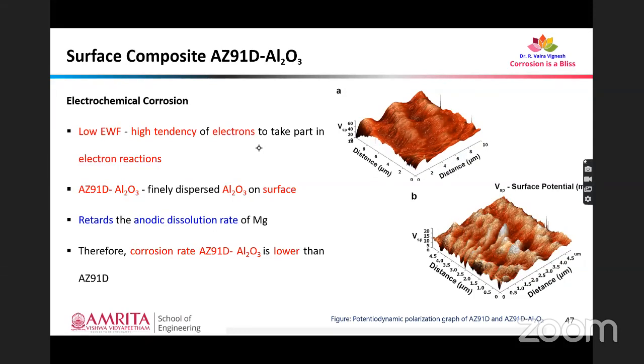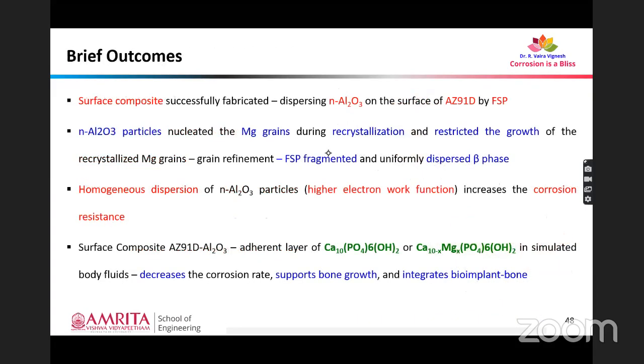So here is the surface potential map that is obtained from AFM, atomic force microscopy technique. Here we have used Kelvin probe microscopy for determining the surface potential. So X and Y axes give us the distance and the Z axis gives the surface potential of the material. So obviously we can see the surface potential was somewhat higher in the nanophase alumina dispersion. So the corrosion rate of this composite is lower than that of the magnesium alloy AZ91D. And these are the brief outcomes of the research.